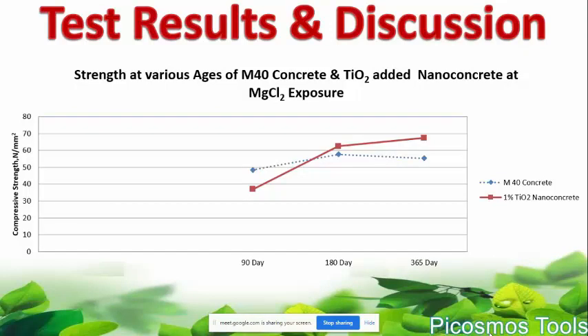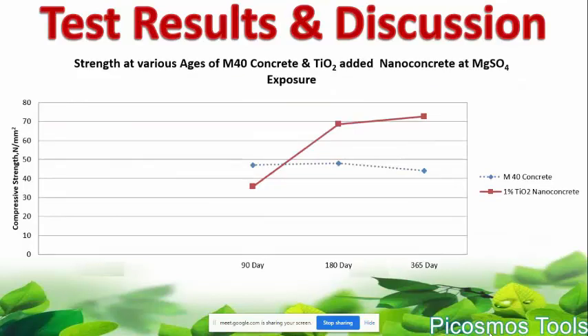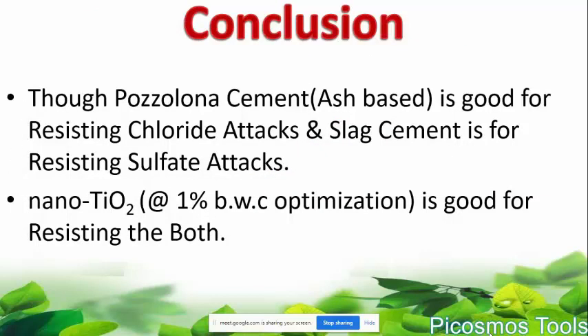My research work results and discussion: at 7 days I am getting this strength of the reference sample. But if I use nano titanium dioxide, see, it is increasing at 28 days, the standard, and in the long term the red line is increasing at 1 year. This is nano titanium dioxide in cement mortar. Microstructure analysis, the same analysis: see the fine uniform microstructure in the nano titanium dioxide sample. And the strength discussion for aggressive environment exposure, MgCl2 exposure: the red line of nano titanium dioxide is giving good strength at 1 year and also 180 days.